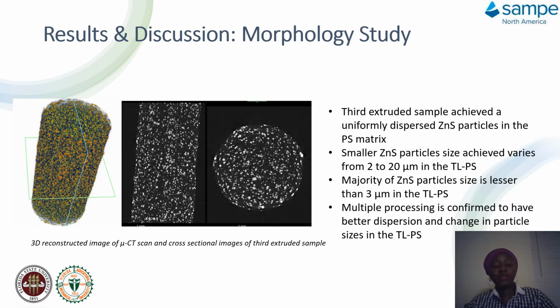And from the surface of the image, we can also see the white particles are the crystals, which shows that they are almost of the same size, about 3 microns, broken down to very small sizes, which is achieved at the third process compared to the first and the second process. This shows that the multiple processing of the filament has a positive effect on the dispersion of the crystals within the composite.